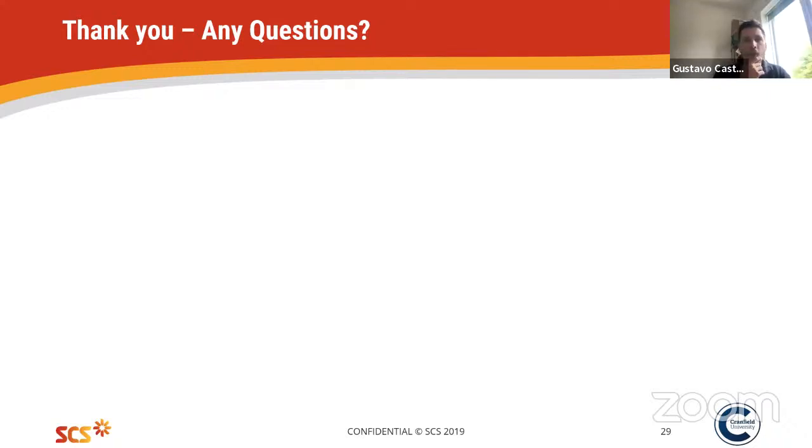There's a question from the audience, and it says, any effects on the surface or bulk properties? Do these changes really matter? Okay, there are surface effects for the same reason we just talked about. So if something deposits on the surface that reacts with the surface, it will change that surface layer. But bear in mind, the laser light can penetrate into the TBC. So in actual fact, what we would see is a signal from within the TBC if we put the additional layers inside, as well as the surface layer. So it might be a method of detecting whether you've got any surface damage.